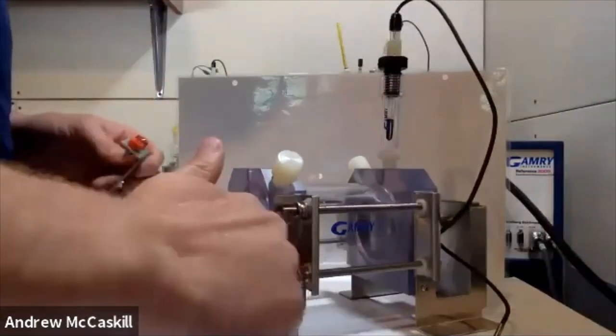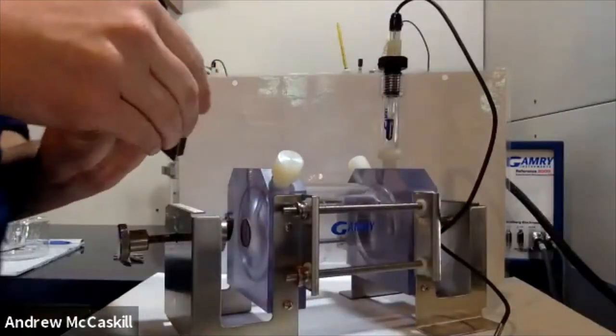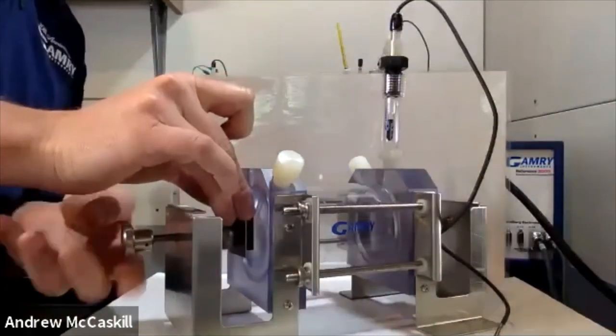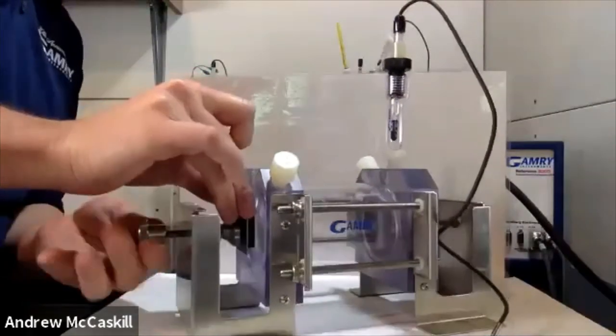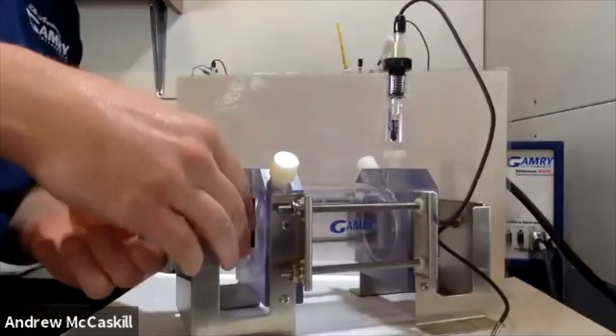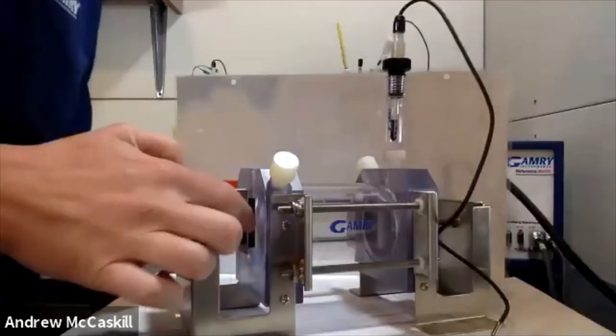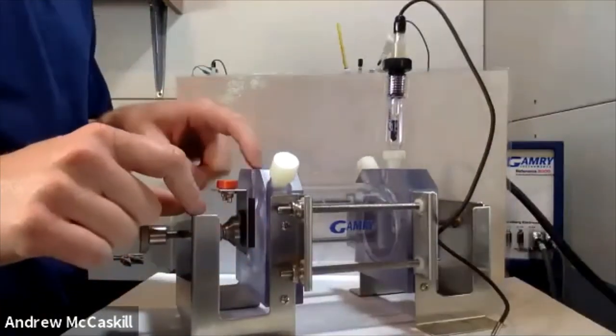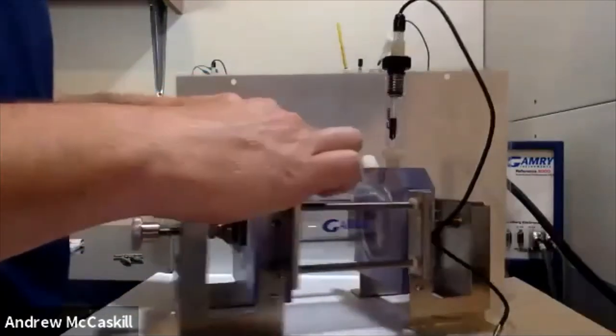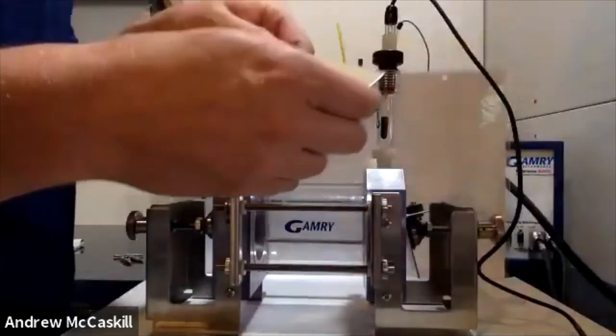Oh, I dropped the block. So I use the pressure of these threads to push the block against and create a seal against the polycarbonate cell body right here. The reason that we have the polycarbonate cell body is if you're using high alkali media, long-term exposure on glass could start to damage the glass.